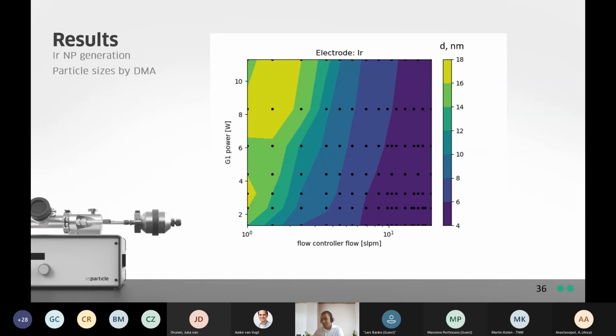So one of the things that we can do quite quickly at VSP is we can determine these particle sizes of the nanoparticles in the aerosol stream. We did this for iridium for this industrial partner. This is done using a DMA, and this plot that I show you here, it's essentially a contour plot. Going from dark purple to light green, we see particle sizes between 4 to 18 nanometers.